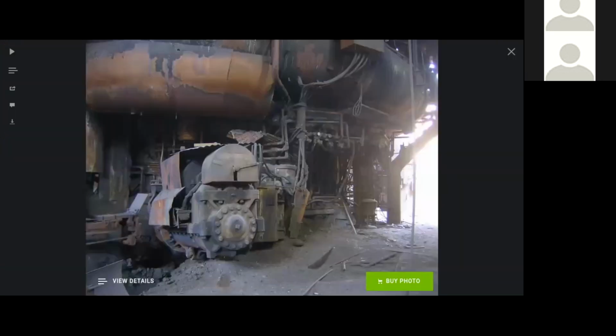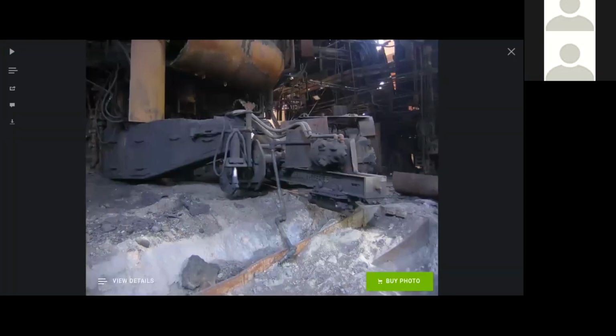And after the iron had been tapped out, this thing here called a mud gun would actually be filled with clay. It would go in and seal up the hole in the furnace, and that would keep the iron from leaking out. So it had to build up for a period of maybe 2.5 hours before it was ready to tap out again. And then to get it out, another piece called a tap hole drill. You can see the back side of it here, and you can just barely see a drill rod coming out. It would actually hammer out and drill out that clay plug that the mud gun put in there. And when this drill got to the end of that plug, molten iron would then come spewing forth out of the furnace.